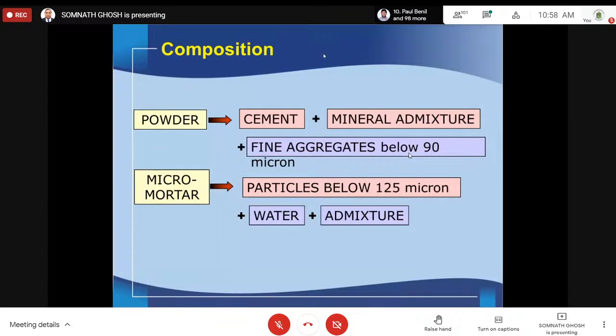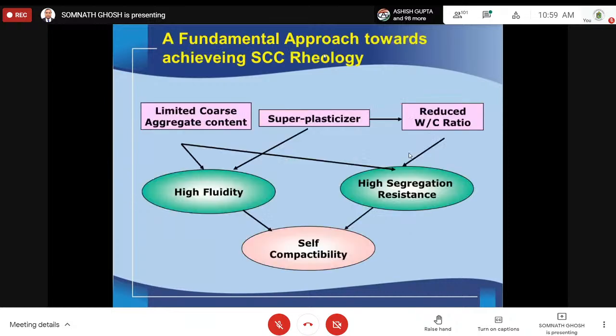Now you see the composition, I told you that powder, the fine aggregate below 90 micron, if you go for very big particles, then it does not always give you self-compacting concrete. Now even micro mortars, we are going for self-compacting also. Particles like below 125 micron. And other things, water, admixtures are there.